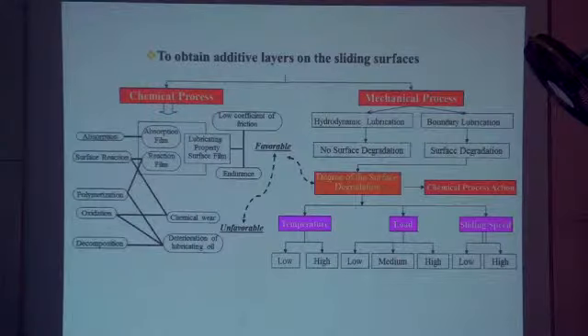In terms of lubrication type, if it is hydrodynamic, with oil separating the two surfaces, we don't obtain the protective layer we wanted. What we want is for all the additives to form on the surface, covering it like painting a wall with a brush. Because in hydrodynamic lubrication, if the two bodies don't touch, there is no surface degradation.